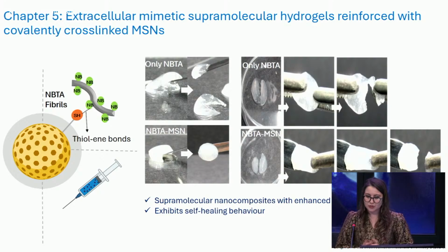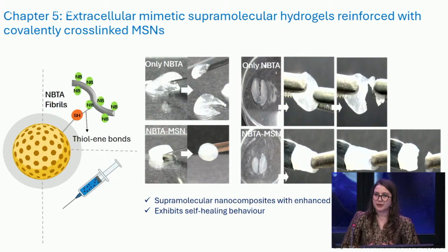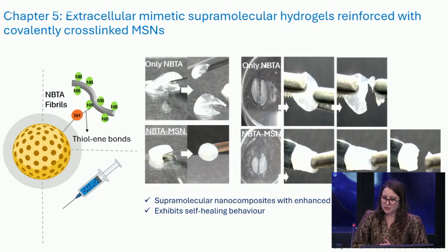In chapter 5, we took a different approach by using MSNs as covalent cross-linkers to enhance mechanical properties of supramolecular BTA-based hydrogels. These hydrogels are particularly fascinating because they mimic the fibrous architecture of the extracellular matrix and rely on non-covalent interactions. However, with many hydrogels based on non-covalent interactions, they tend to have weak mechanical properties, which limits their practical applications. So to address this challenge, we designed a hybrid network.